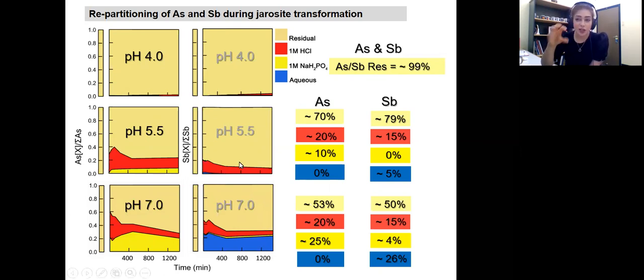But if they are bound to the surface, as happened to arsenic here, a 10% increase on the surface, then it probably is the case that we will see the release of arsenic to the environment. So we observed that for arsenic, but we didn't see the same thing for antimony. It stayed in the structure, or it was locked in the poorly crystalline phases that were extractable with molar HCl. And a little bit of aqueous release of antimony was observed at pH 5.5, which wasn't that significant, about 5%.